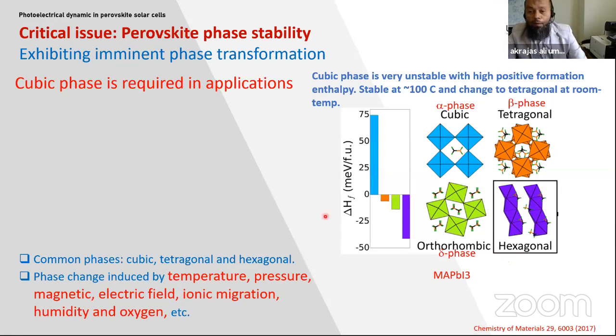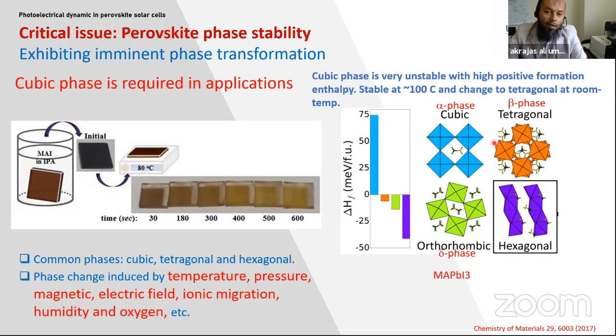In a high performance optoelectronic device, the cubic phase is required, but this phase is only stable at high temperature because of its high positive formation enthalpy. By changing the temperature to room temperature, it can easily change to tetragonal, which is not optically active. So this means that our device using this material will not function. This is a typical example of how the phase transformation can be seen.